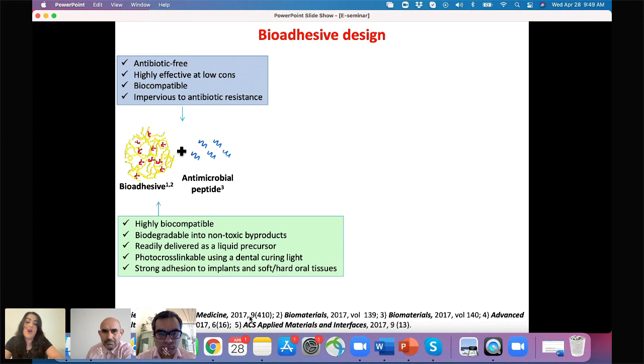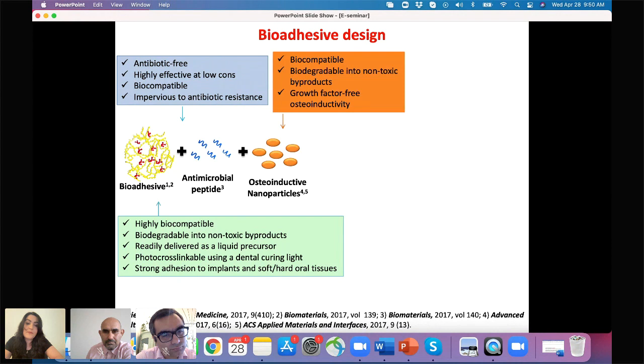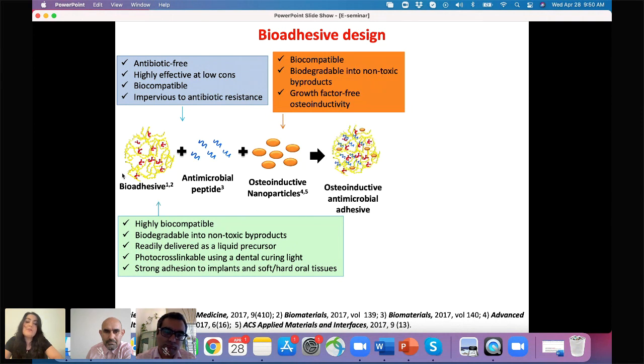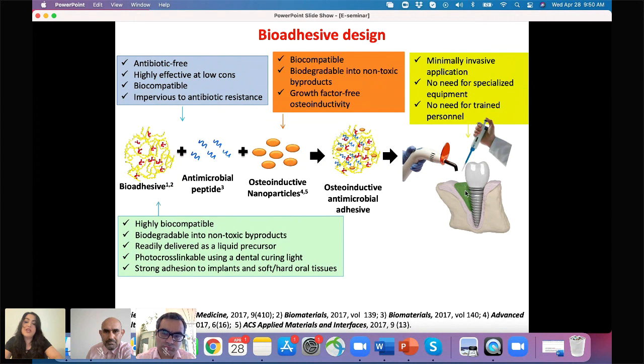We have shown in our publication that antimicrobial peptides are very effective at low concentration. They are biocompatible and they won't cause antibiotic resistance. To make this biomaterial also osteoinductive, we combine it with osteoinductive nanoparticles, Laponite, and these are biocompatible nanoparticles that can degrade into non-toxic byproducts, and we can use it as a growth factor-free approach to make our biomaterials also osteoinductive. So we optimize the concentration of all these elements to form this photocurable hydrogel, which can be injected around the implant. Once we inject it as a liquid, it can fill all the voids and cavities here. And then by using a dental curing light, you can photopolymerize it.